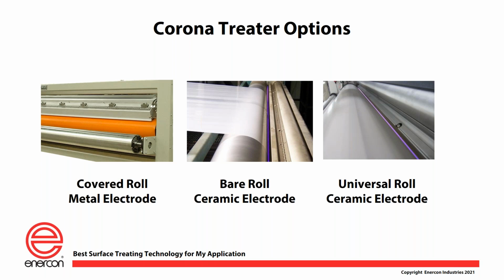So the options you have with corona treaters are a metal electrode, covered roll metal electrode, and that metal electrode can be fixed or it can be segmented. You could have a ceramic electrode, which is basically a ceramic bar, or a pair of bars that are housed and then mounted above a bare roller or a roller that has a conductive ceramic applied to it. The most popular corona treater of the three listed is the final one, and that's a universal roll treater. That treater is used pretty much all the time in converting applications. So if you're printing, coating, or laminating, this universal treater, which has ceramic electrodes and a ceramic coated roll, is really the right choice for those applications.